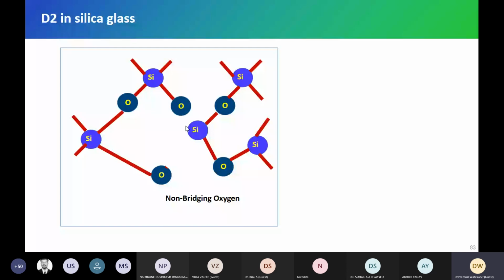So how to avoid that? Hydrogen is always there, because we have polymer coatings that are made of hydrogen. There's a lot of hydrogen there. It can diffuse out, diffuse in. The environment has hydrogen. If you keep it for many years, 5 or 10 years, hydrogen can enter there. And if hydrogen enters, there will be huge loss, attenuation, and your network will fail because of that attenuation. It is not a matter right now, but in future it is going to fail our fiber. All systems will collapse because of this hydrogen diffusion in the fiber.